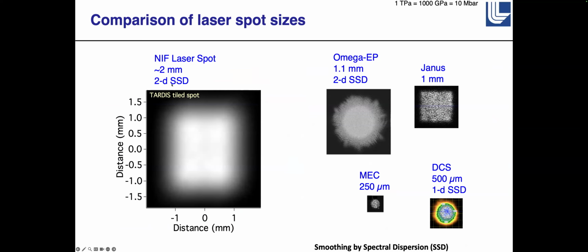This is the relative sizes of the laser spots. NIF has a very large spot that we use to do the diffraction. At Omega, it's substantially smaller, but the energy of the laser is smaller. And Janus at Livermore is smaller still, with smaller energy. DCS is at the APS, a synchrotron in Chicago, and MEC is at the LCLS XFEL in Stanford. And those lasers are much smaller, so we focus them down a lot.